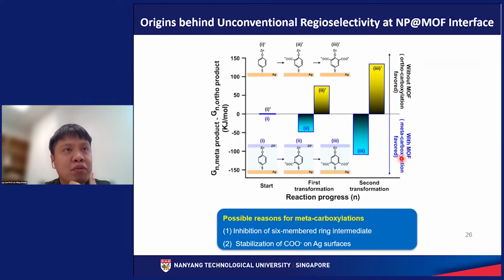Okay, so there are two possible reasons for this meta-carboxylation. So this could be due to the inhibition of the 6-member ring intermediate. So the coordination of the oxygen atom over here with the MOF, with the zinc constituent of the MOF, can prevent the formation of the 6-member ring intermediate. So this could be a way for us to kill the usual ortho-selectivity in a KS reaction.